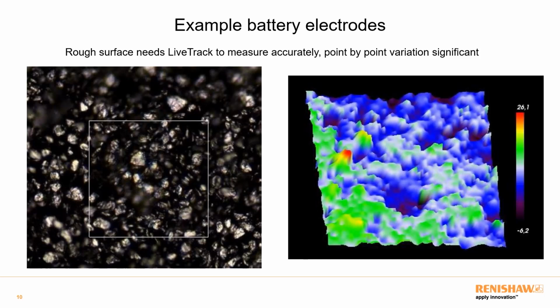My next example is a battery electrode. This shows another circumstance where LiveTrack is really powerful. In this case, we've got a surface which is very rough. So if you conduct a Raman map over this surface, you'll have areas where you'll go in and out of optical focus, and that will start to present artifacts in your results. In most cases, the way you'd get around this is to compromise, go to a lower magnification, lower NA lens, and then that affects your Raman performance.